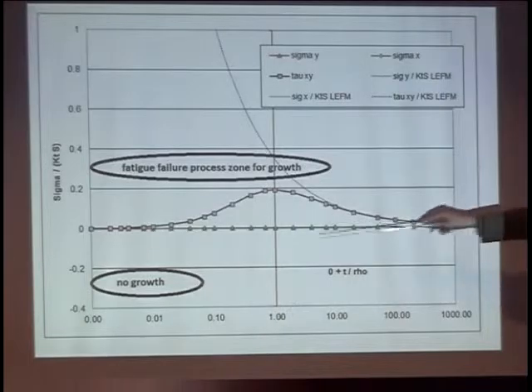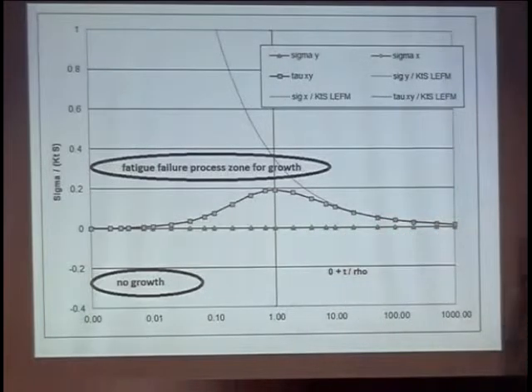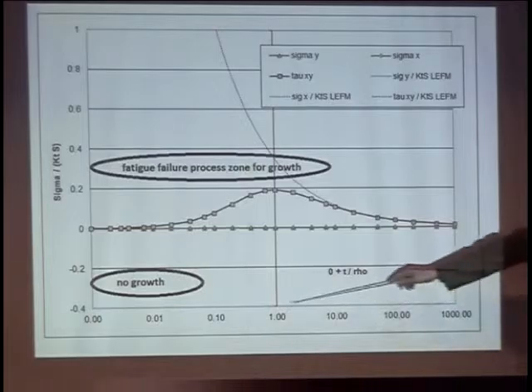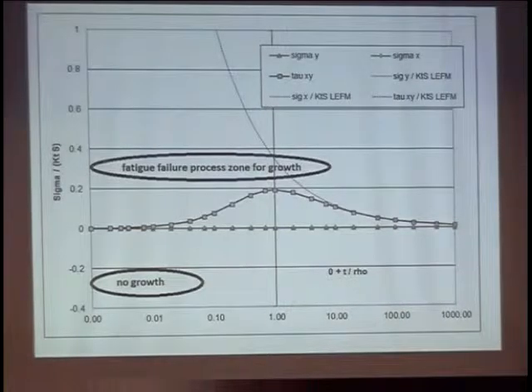And so to say the process zone is this small would be nonsense in terms of plastic zones. This value of rho is of the order of the crack growth increment per cycle. It's tiny, and the plastic zone is much, much bigger. So I still believe very much plastic zones or high strain zones or something like that are process zones for deformation, for the cyclic deformation that drives a crack. What I told you in the chart was that there were two process zones. Why should there be only one?